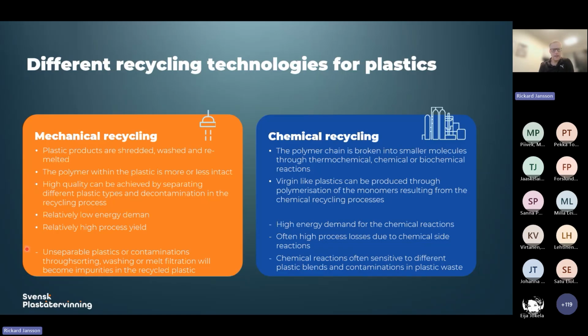The negative or difficult part to handle is when you have plastics that you cannot efficiently separate during the sorting or recycling process, which means that you potentially end up with a mixed polymer material within the pellets, which can potentially give poor mechanical properties of the recycled material. And you also risk having contaminants or impurities within the material.